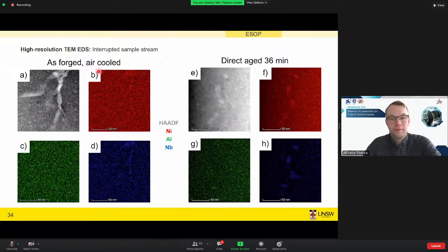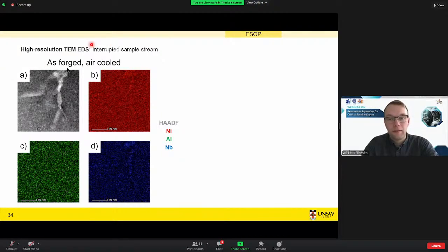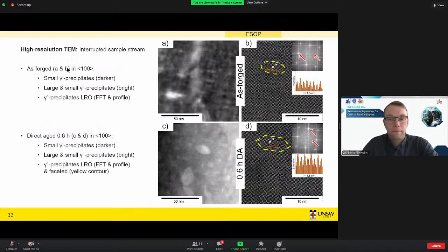Dr. Wahyu, that's a very short question because I'm really curious about your result using TEM. You showed us slide number 33. Could you show it to us again? You mentioned that it is a high resolution TEM image, right? And then you can also get the atomic, in the nanoscale structure. So I'm just curious, you set the G factor by the TEM, right? In this case, the direction of the diffraction patterns in B and D for the gamma prime.